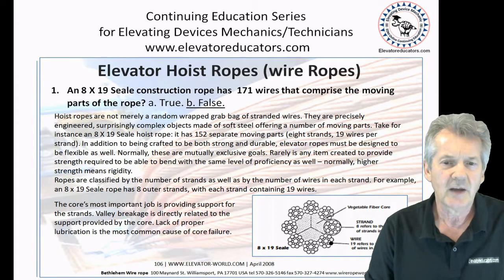Ropes are classified by the number of strands as well as the number of wires in each strand. For example, an 8x19 seal rope has 8 outer strands, with each strand containing 19 wires. The core's most important job is to provide support for the strands. Valley breakage is directly related to the support provided by the core. Lack of proper lubrication is the most common cause of core failure.